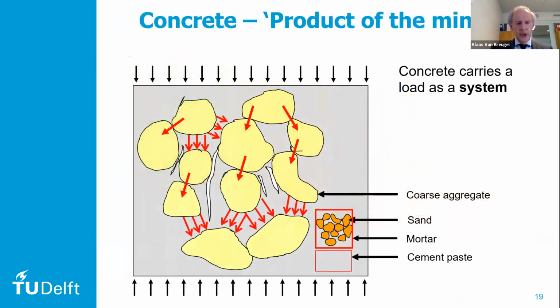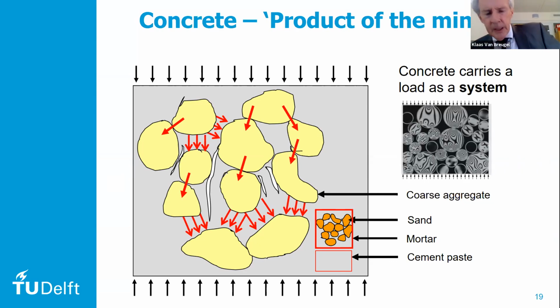Let's go more in depth into concrete and what happens when it is loaded. When it is loaded, you see here a piece of concrete loaded, and you see that cracks occur. Here you see that the cracks are occurring. The load is transferred from one side of the sample to the other, and it causes cracks because it's a very heterogeneous material with all kinds of stresses in it, tensile stresses, and concrete will then crack. And the load will be transferred via the aggregates and via the cement paste, and the cracks, but still the cracks are there.